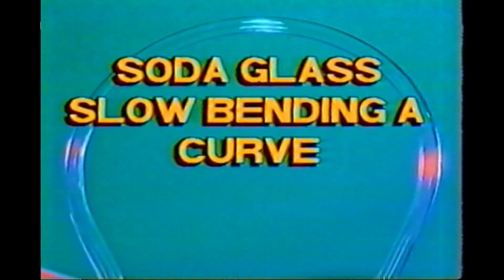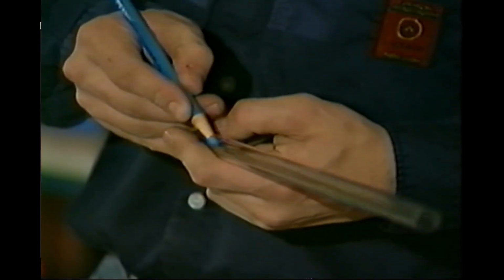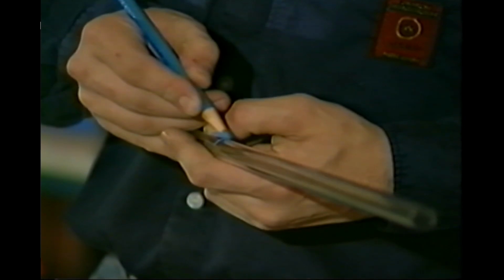Another method of producing a curve popular in many countries is by slow bending. This technique is ideal for both colored and soda lime glass and is demonstrated here using clear tubing. Mark the center of the tube length with a chinagraph pencil. This mark must be lined up with the center line on the drawing every time the tube is fitted to the pattern.